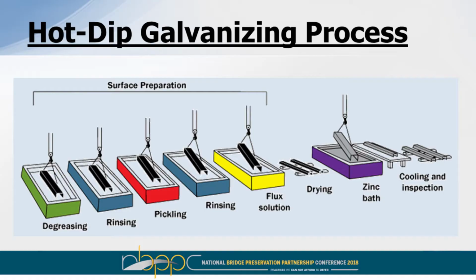We then rinse that. It then goes into a pickling process. This can be either a hydrochloric acid solution or a sulfuric acid solution. It's about 50-50 in the United States. It's basically the preference of the galvanizer. Sulfuric lets you go a little bit quicker, but it's a little bit more aggressive, so you've really got to be careful. You've got to have a good operator.